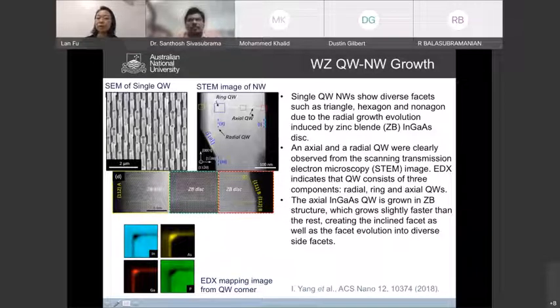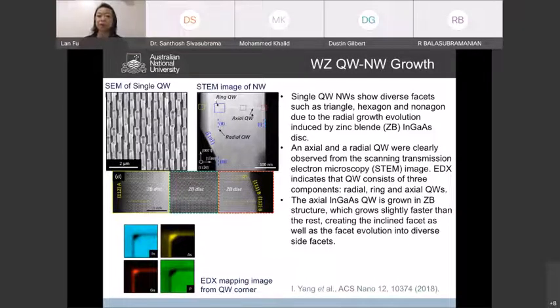As we know, nanowires have multi-faceted structures, and the surface energies are very different for different crystalline structures. It turns out that when we insert indium gallium arsenide into the nanowire structure, it wants to form the zinc blende structure, rather than the wurtzite structure we had for the indium phosphide at the beginning. Thereby, the growth rate along different facets of the nanowire becomes different, and that leads to this very irregular shape of the quantum well incorporated nanowire.